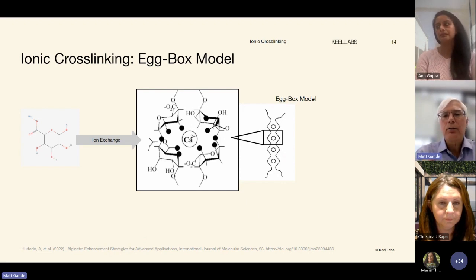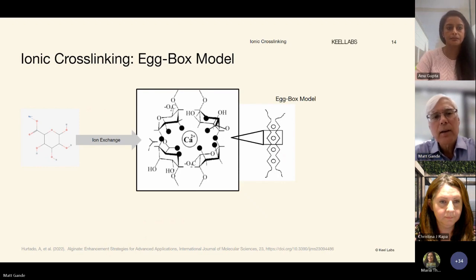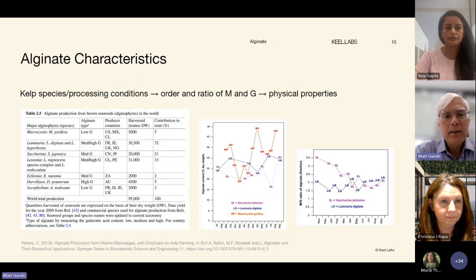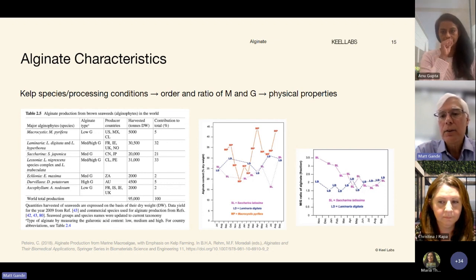And by doing that, you're now cross-linking these polysaccharide molecules together, and that's what makes it insoluble, as I said, for the precipitation part, but it's also critical in forming fibrous material from the alginate, is these ionic crosslinks that can be formed in the backbone of the material. As I said, how the G blocks and M blocks are in there can affect some of the physical properties that are there.